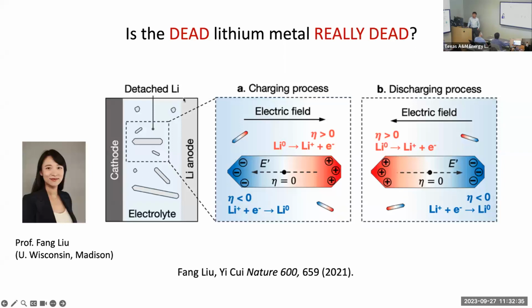Now, imagine once you do a charging process, you apply current between cathode and anode, and this ionic current inside the battery cell and the electrolyte. You're going to have an electric field from cathode to anode inside this organic electrolyte. Even though this isolated metallic lithium is not connected electrically, this electric field inside the battery cell is going to polarize the metal. Metal can be polarized in a perfect sense, right? So this polarization will create an electric field against the external electric field inside the metal. We know inside metal there's no electric field in the steady state.